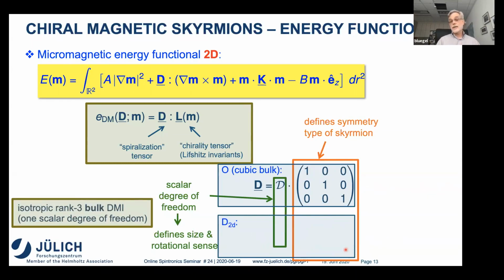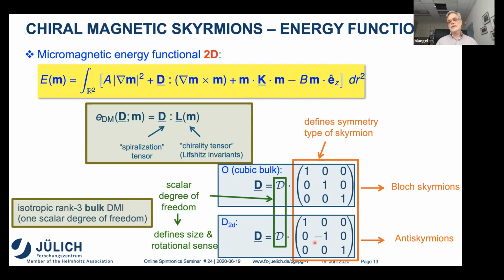And there are other crystals, for example, crystals with D2d symmetry. Due to the symmetry, they have different tensor elements. And this tensor element gives you, for example, an antiskyrmion. Well, this we discussed already as a Bloch skyrmion. So depending on which crystal structure you choose, you get either a skyrmion or an antiskyrmion. And we have recently found out that if the determinant of such a tensor is positive, then you have skyrmions. If it's negative, you have antiskyrmions.